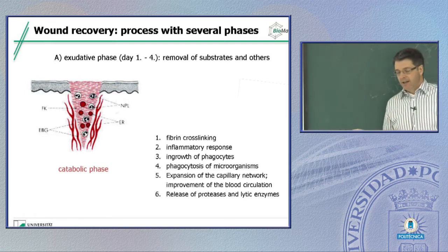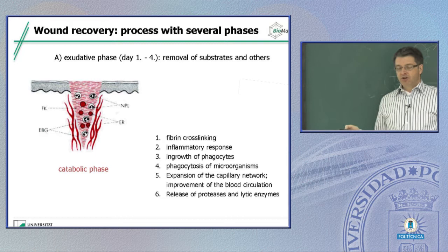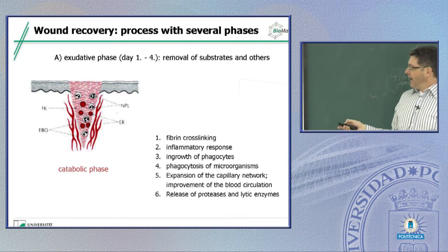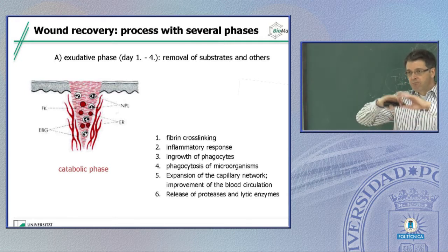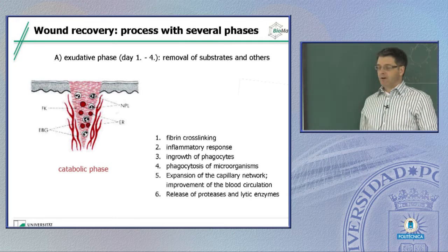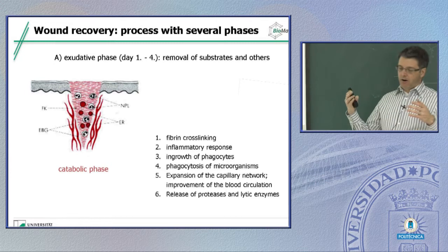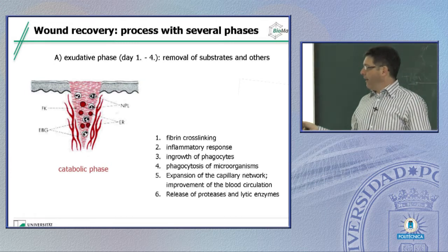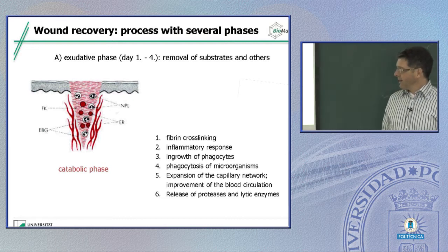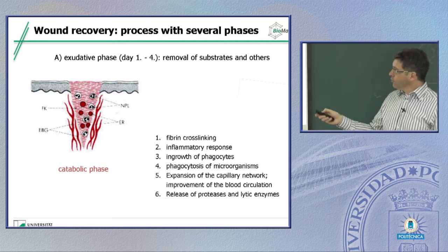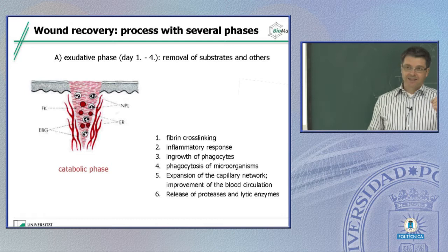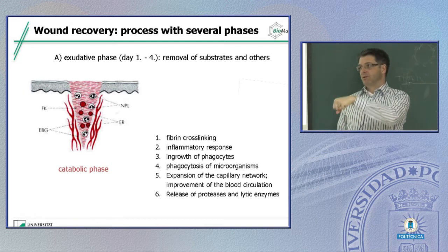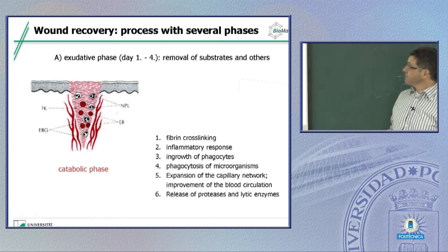And what we did, we developed an in vitro model in the lab where we actually can mimic the whole mix of proteases. So there is a collagenase, and there are different metalloproteases that are secreted here. And we have that in the lab, so we can mimic this wound solution and can then test scaffolds inside that wound, if they're stable or not, for instance.